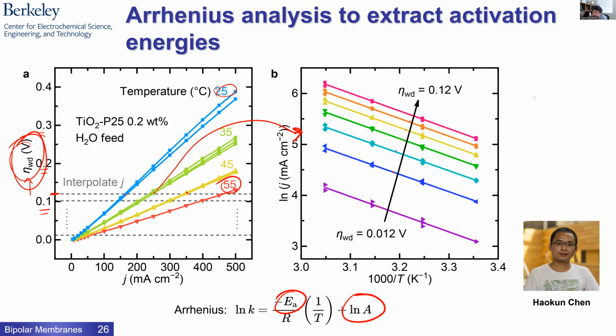Because in electrochemistry, when we think about voltage-induced charge transfer reactions, we often invoke pictures of things like the Butler-Volmer model, or you might think about a Marcus model. They're similar models of how charge transfers. And usually you might draw something like this. So if this is my reaction coordinate and energy, I might draw a precursor state, and as I move through the reaction, say I have some oxidized species plus an electron in my electrode, and I have some reduced species here, and I want to know the rate at which that reaction occurs as a function of driving force.